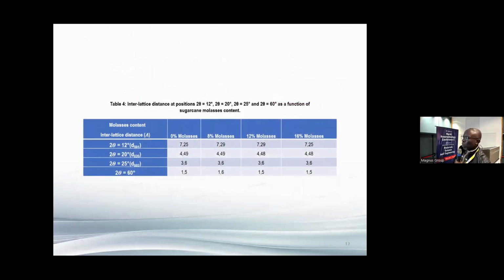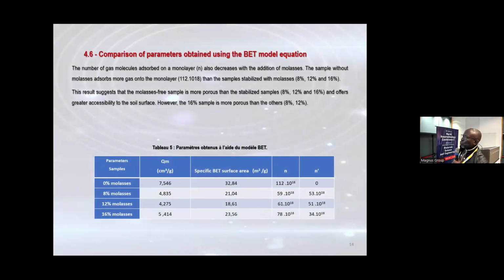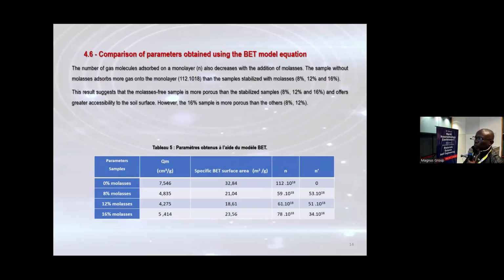This is the interlattice distance of position. Comparison of parameters obtained using the BET model equation. The number of gas molecules adsorbed on the monolayer also decreased with the addition of molasses. The sample without molasses adsorbs more gas into the monolayer than the sample stabilized with molasses 8%, 12%, and 16%. This result suggests that the molasses-free sample is more porous than the stabilized samples, 8%, 12%, and 16%, and offers greater accessibility to the soil surface.